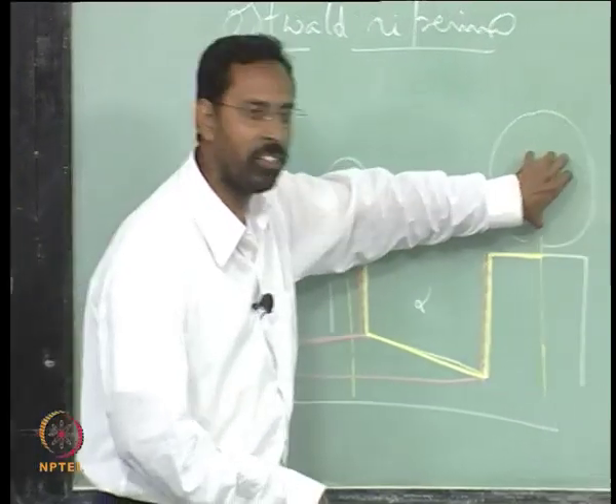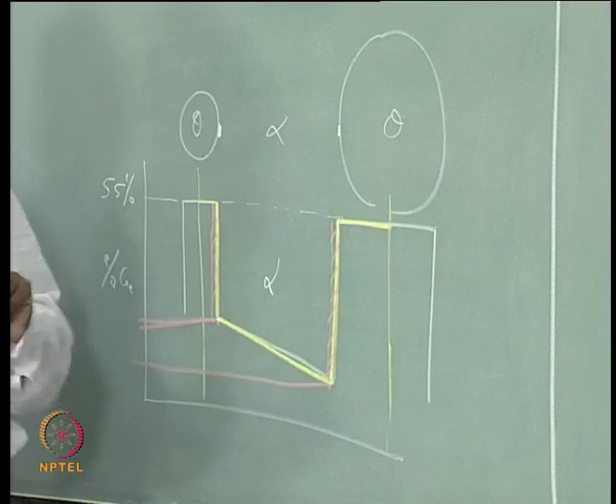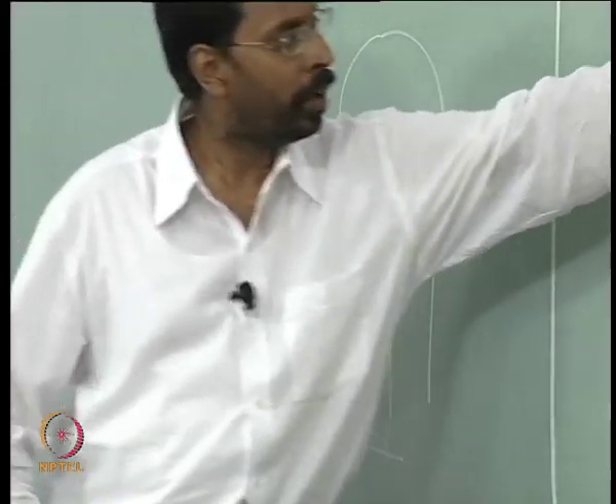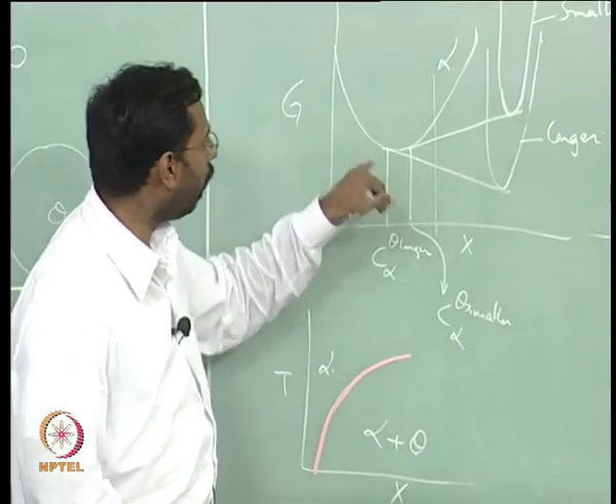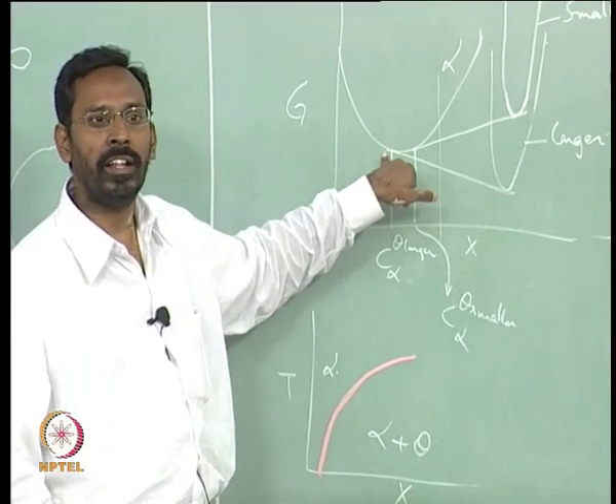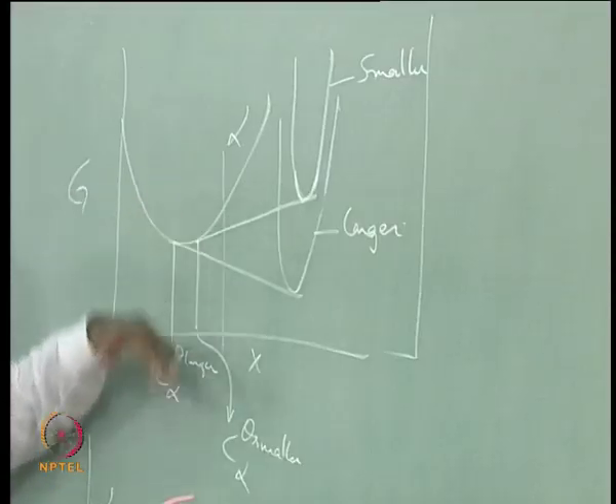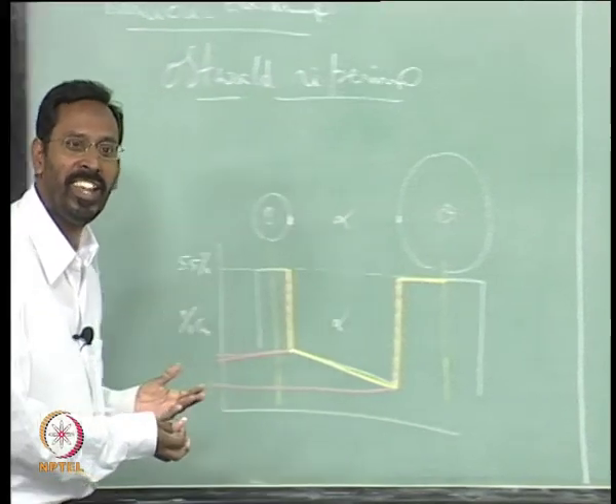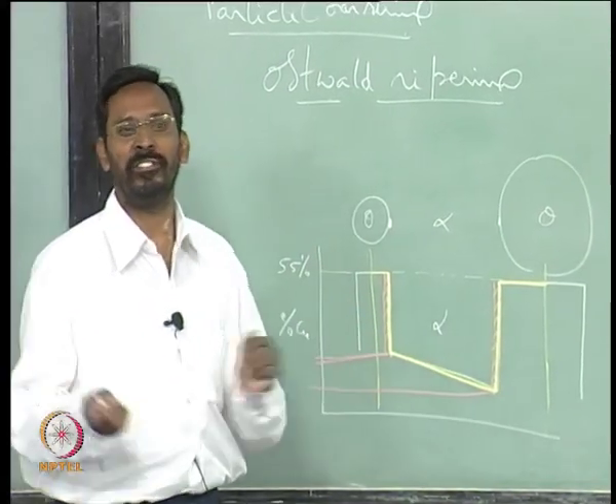And what happens to this? As this starts becoming larger and larger, this free energy value comes down, and that means the common tangent, again, the copper content of alpha comes down. That means you actually see that the gradient is increasing,